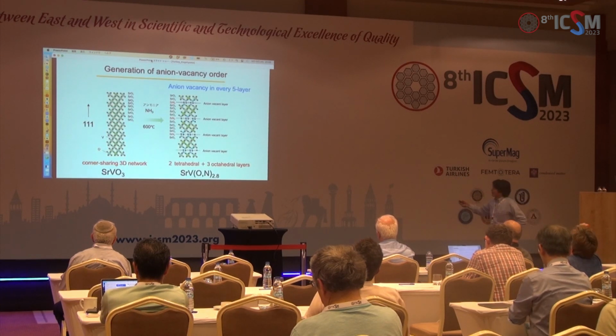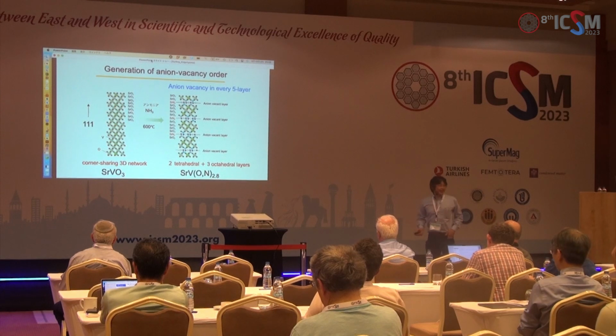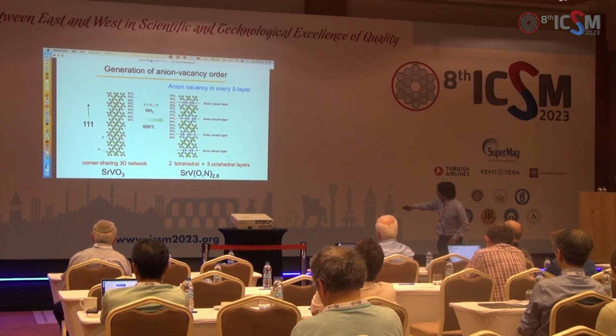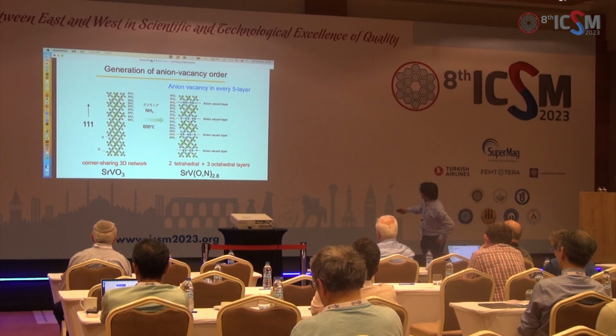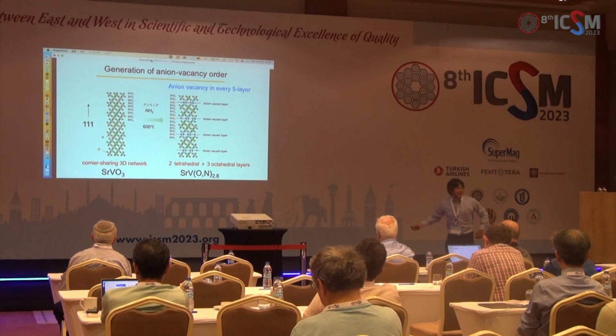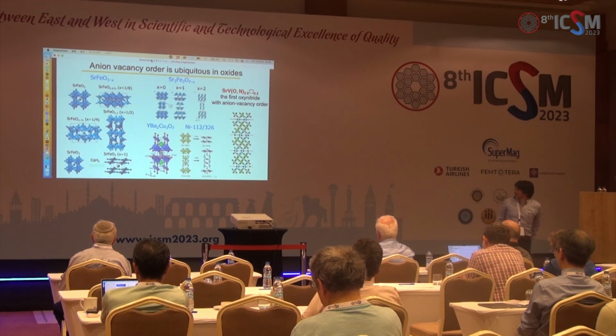Then we found that there is the oxygen vacancy order in every 5 layers, as you can see here. So originally we have a corner-sharing 3-dimensional network of vanadium O6 octahedra. But after this reaction, we found that we have a kind of alternate stacking of the double tetrahedral layer and the triple octahedral layers. So we have a two-dimensional structure by using chemical reactions.